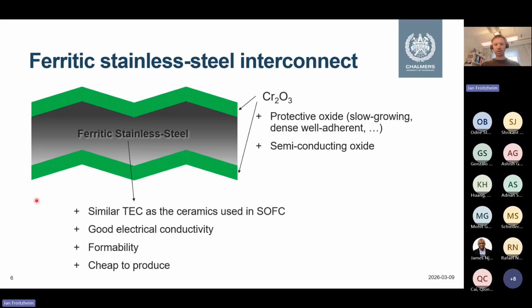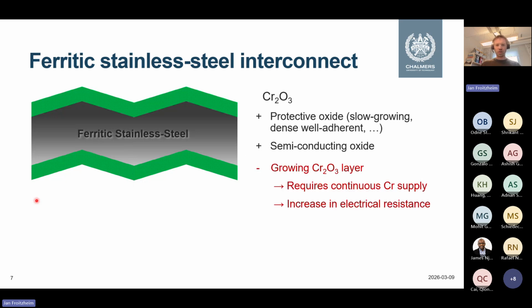And so we basically get a chromia scale, Cr2O3. And that is good because that protects the steel from further corrosion—it still corrodes, but it corrodes slowly. And the chromia is reasonably conductive. However, it's not a great conductor compared to other oxides, particularly those used in, for example, the air electrode. So it increases the electrical resistance with time.